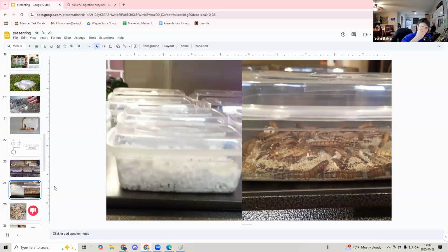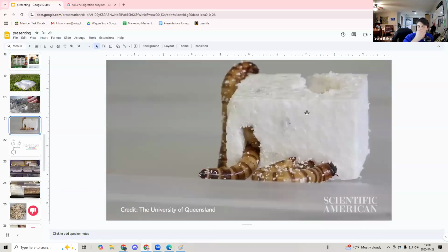So, what if instead of feeding the worms large chunks of plastic, we scale the plastic down in size? What if we take the foam of the plastic, which is a material that is mostly air? Styrofoam plastic is something like 95% air by volume, and we densify it. The reason we want to densify it is because the worms, as I mentioned, are chewing into this and digesting it, and a lot of the digestion work is really happening because of the microbes in their gut. So if we can make the plastic denser, maybe every bite they take, they'll get a lot more plastic out of it, and then a lot more plastic will be digested a lot more quickly. So, we try and shrink it down and see if that makes the whole process faster.